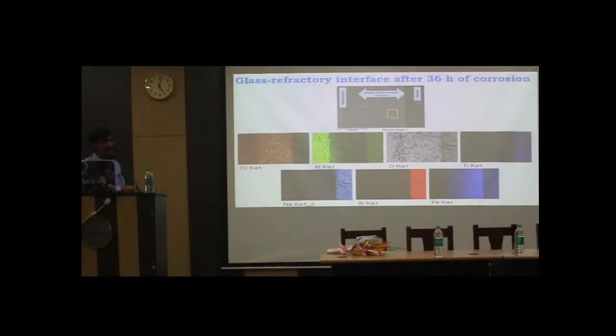Now, from elemental analysis, or if you want to do some mapping, then we have some idea. Suppose this one is the 36 hours. You see that the chromium concentration is more or less constant, and this is the glass side, and absolutely there is no chromium in the glass. But in the case of aluminium, up to this portion, this is the refractory. But you see that in the corroded region, the aluminium concentration is much less.